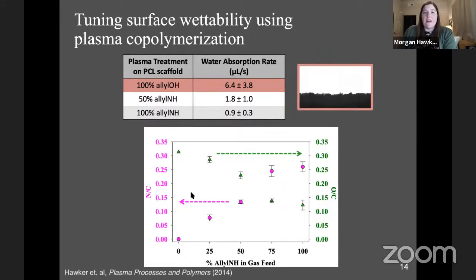What we're looking at here is that the oxygen to carbon ratio decreases as a function of allylamine in the gas feed, whereas the nitrogen to carbon ratio increases, generally speaking. So these data demonstrate that the amount of nitrogen containing functional groups on the surface increases with the amount of allylamine in the gas feed. And you'll notice that both nitrogen and oxygen are referenced to carbon. You might be wondering why that is. That's because the carbon content was found also via XPS to be effectively constant between the different surfaces. So these data indicate that plasma copolymerization can be used to concurrently tune the nitrogen content on the scaffold surface as well as its wettability.